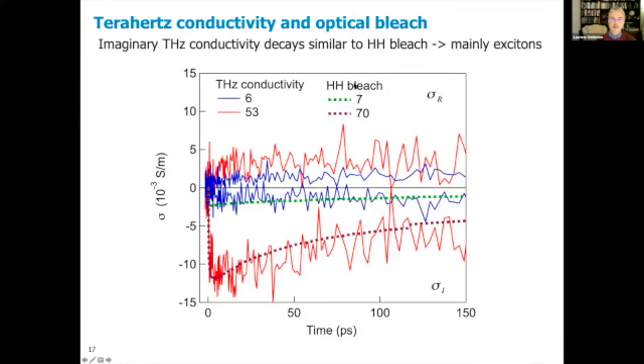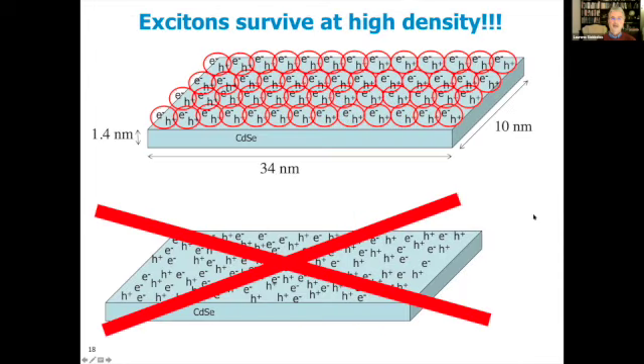So if you now look at the signals of this heavy hole bleach signal for values of the number of photoexcitations per nanosheet close to those in the terahertz conductivity measurements, then you can see here the decay of the transient optical absorption for 7 electron hole pairs per nanosheet, and here for 70, which is somewhat higher than the 53. And you see that the relative magnitude of the heavy hole bleach, the optical response, follows that of the terahertz response, and also the decay kinetics are similar. So that suggests already qualitatively that we have excitons all the time, that they survive at high density, and that we don't get a transition to an electron hole plasma where you have uncorrelated electrons and holes moving through each other.